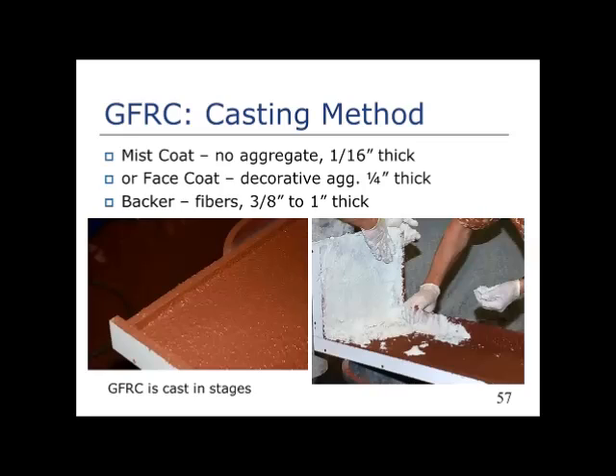Now, a lot of people just use the term face coat, and although it's technically specific to decorative aggregate, it means it's the part you see. It's like your veneer coat. The backer, in the case of the right-hand picture, the white stuff, that's the GFRC. That has the fibers in it. The mist coat and face coat don't have the glass fibers in them. The backer has the fibers, and that's laminated and cast in layers, anywhere from 3/8 of an inch thick up to 1 inch thick or so. But generally, it's put in 2 layers that are each 3/8 of an inch thick, so we get a 3/4 inch thick backer layer.